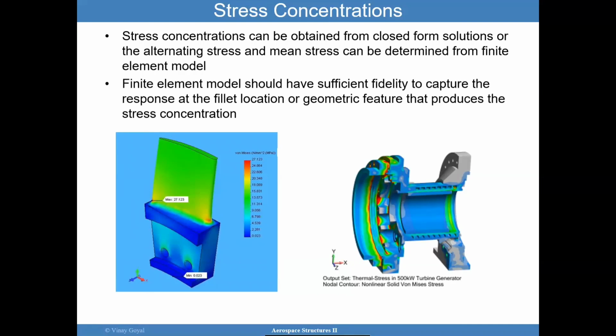There's a turbomachinery part. You can see that stress concentrations can be obtained from closed-form solutions. You know that, we just covered that, and in the homework you'll be doing plenty of that. The alternating stress and mean stress can be determined from finite element models. The finite element models should have sufficient fidelity to capture the response at fillet locations or geometric features that produce a stress concentration. The point I want to make is that stress concentrations do affect fatigue life quite significantly, and so it's important to understand that those need to be well characterized in your models.